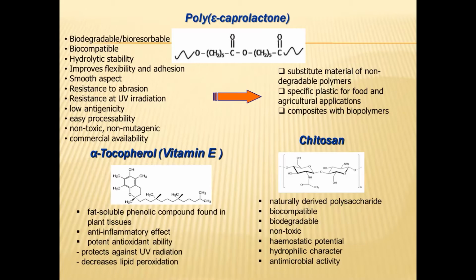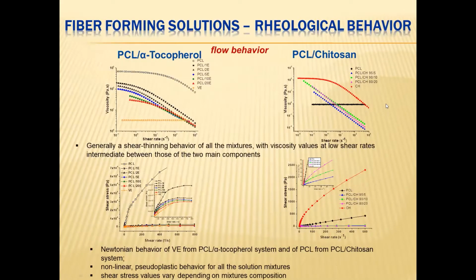process. In order to obtain uniform continuous fibers by electrospinning, the rheological behavior of the fiber-forming solution mixtures should be investigated in order to assess the influence of blend solution composition on the flow behavior and viscoelastic response in view of the electrospinning conditions. Therefore, the rheological behavior of the fiber-forming solutions was studied.